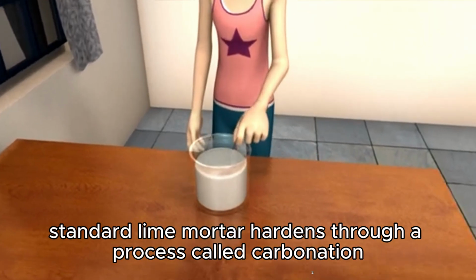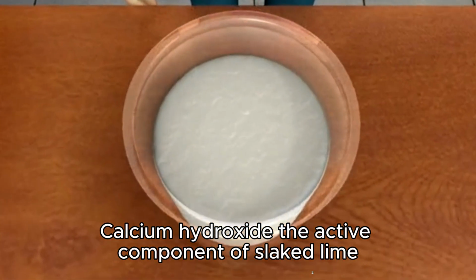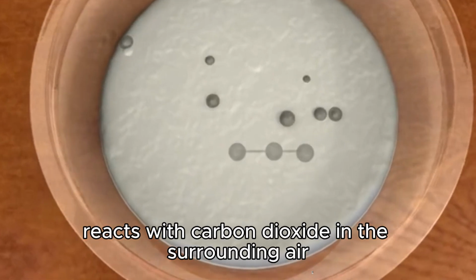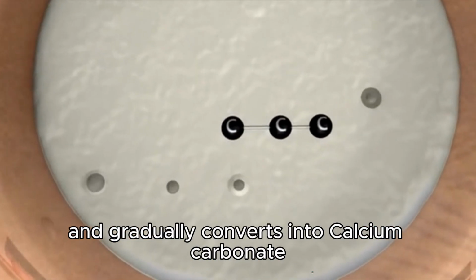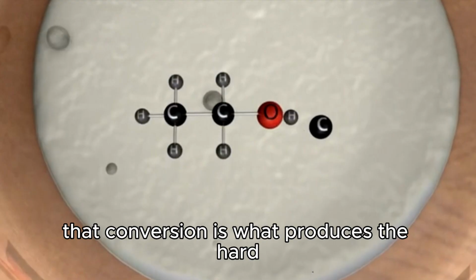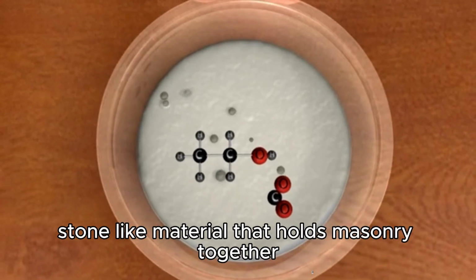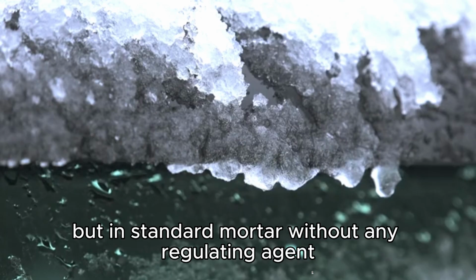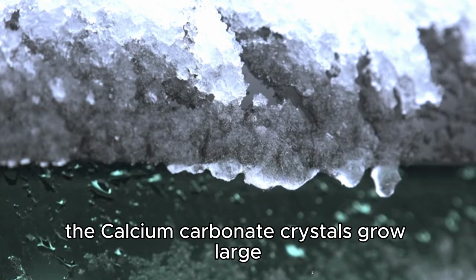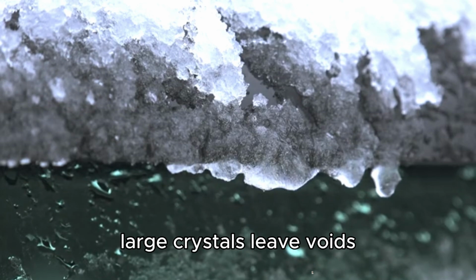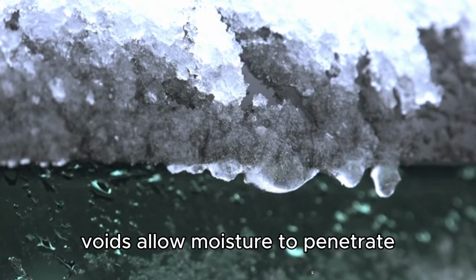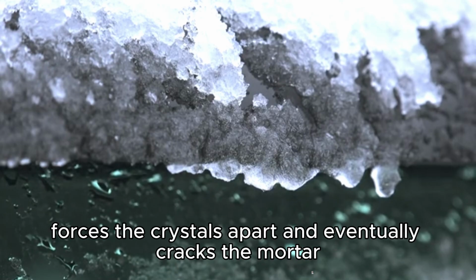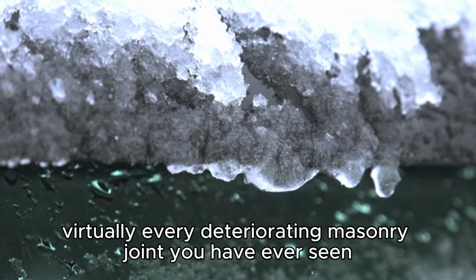Here is why that matters. Standard lime mortar hardens through a process called carbonation. Calcium hydroxide, the active component of slaked lime, reacts with carbon dioxide in the surrounding air and gradually converts into calcium carbonate. That conversion is what produces the hard, stone-like material that holds masonry together. But in standard mortar, without any regulating agent, the calcium carbonate crystals grow large, irregular, and loosely packed. Large crystals leave voids. Voids allow moisture to penetrate. Moisture expands during freezing, forces the crystals apart, and eventually cracks the mortar. This is the failure cycle behind virtually every deteriorating masonry joint you have ever seen.